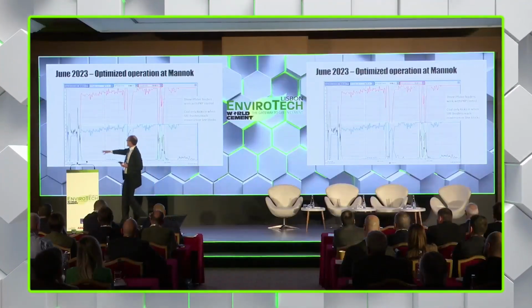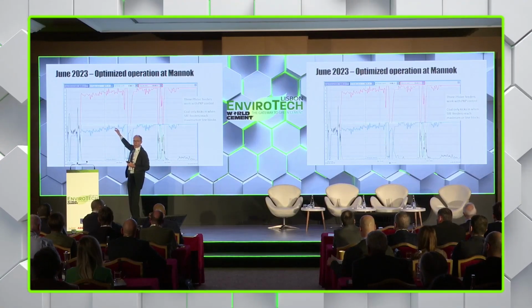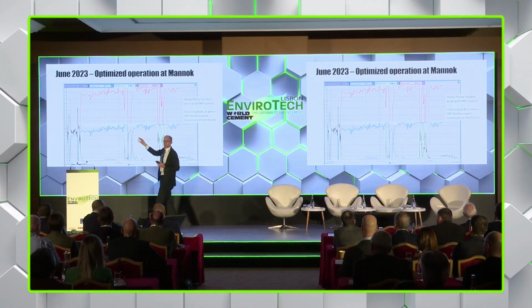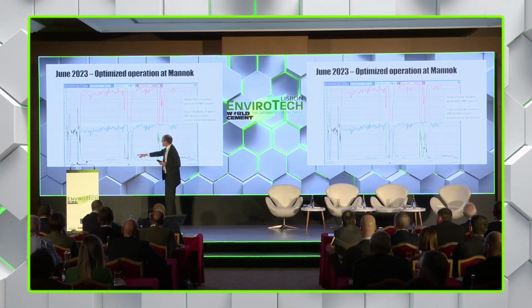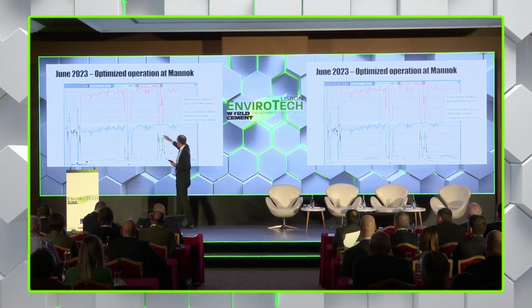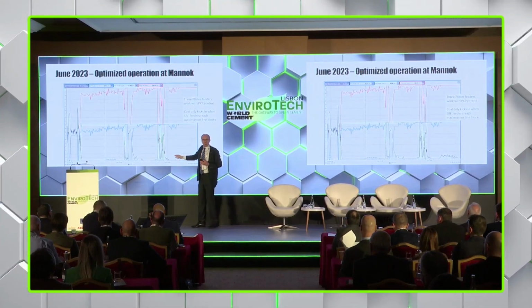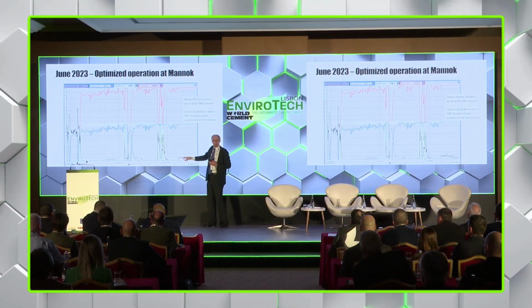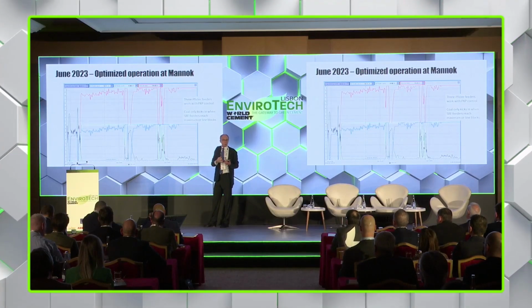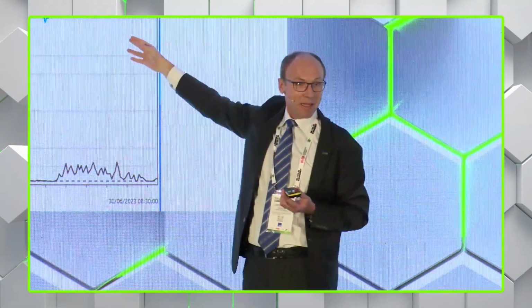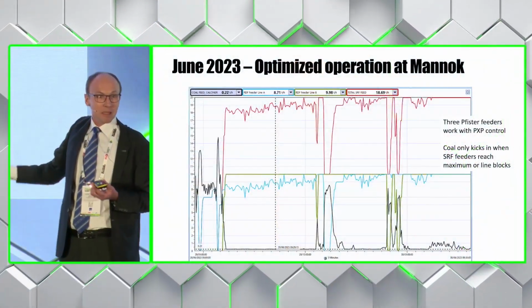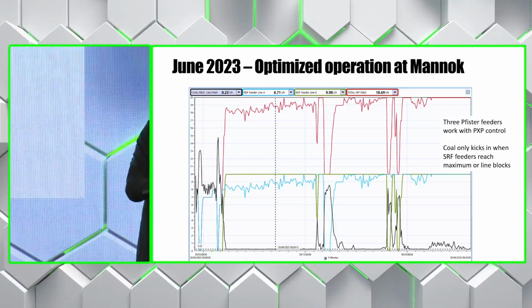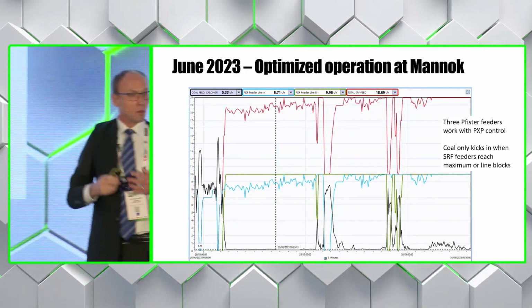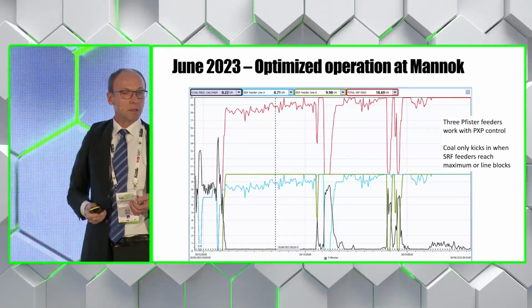It remains down here, and the process is controlled by the alternative fuel being admitted to the calciner. Every time the fuel might fail, the coal kicks in and otherwise goes down to a minimal. What you'll notice at the end here is that then the coal takes over. And this is because the alternative fuel calorific value has been dropping over time. So you need more and more alternative fuel, and in the end there's no more capacity in the feeders, so the coal feeders take over. But this has been extremely effective to really minimize the coal consumption at Mannok, so showing how it's important to look at the process as a whole.